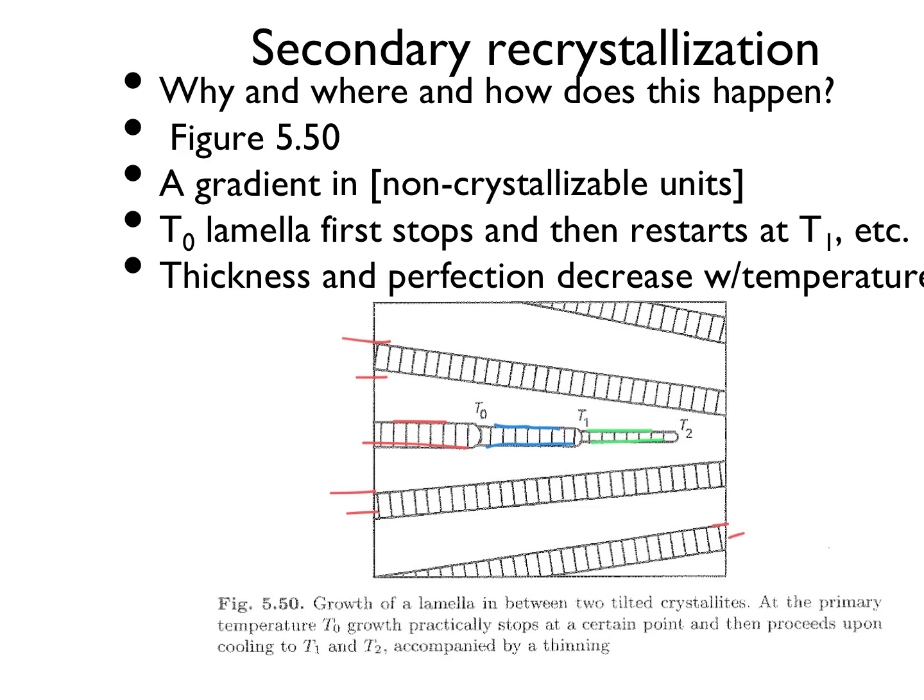And so what you're looking at here is not an arbitrary jumble of figures. This is actually what's occurring inside of a spherulite. The spherulite is finding, nucleating, and growing crystals, and crystals that require a lower temperature to nucleate and grow are showing up epitaxially on other previously nucleated crystals.